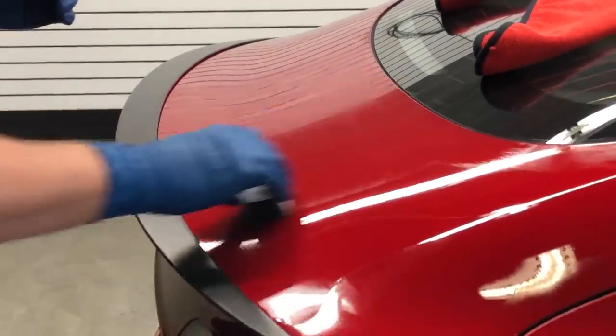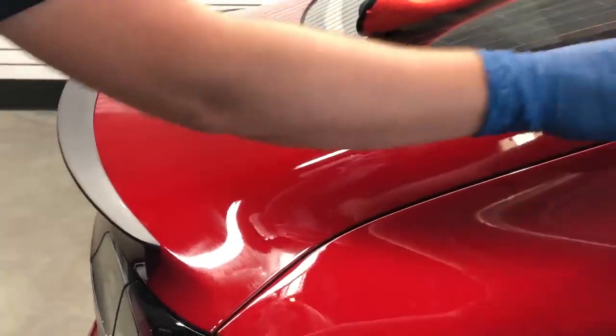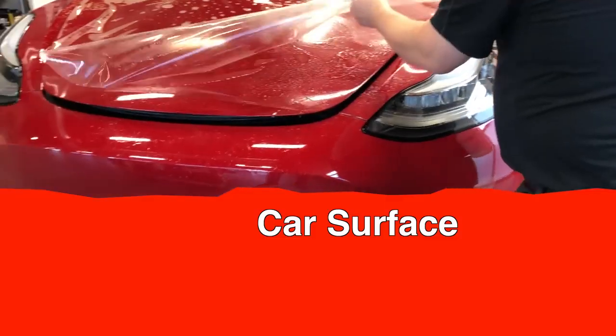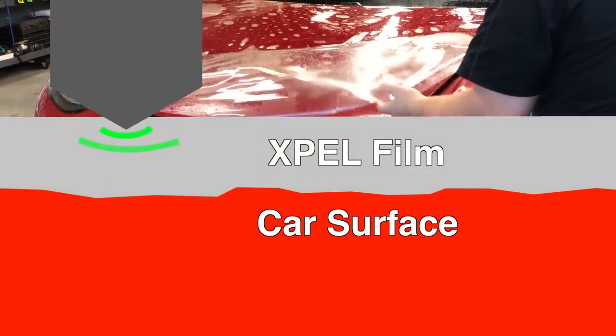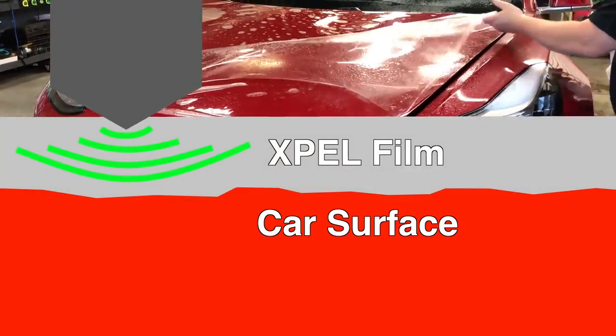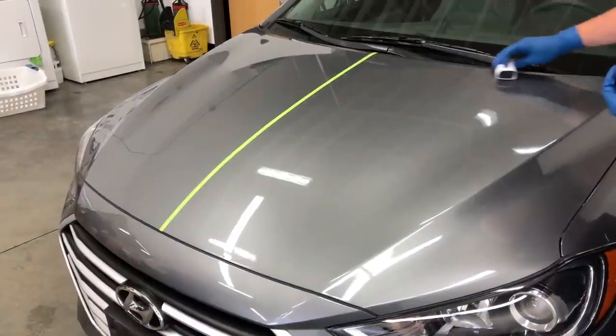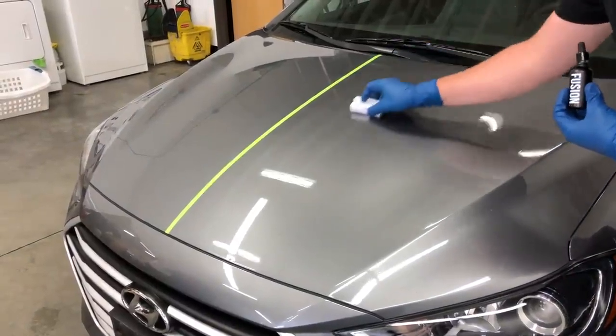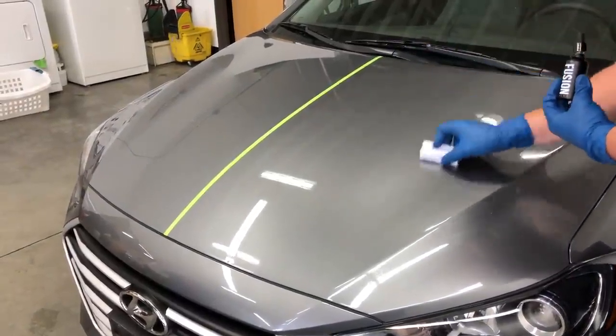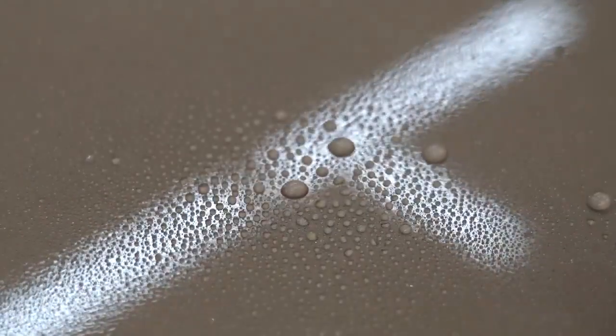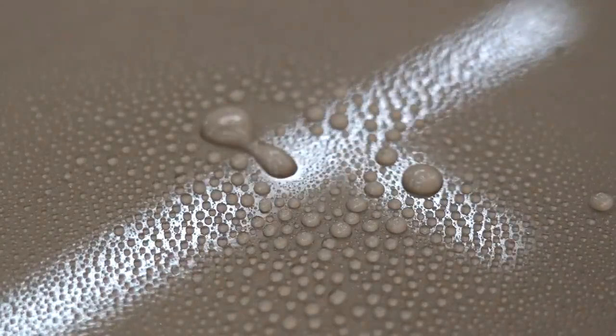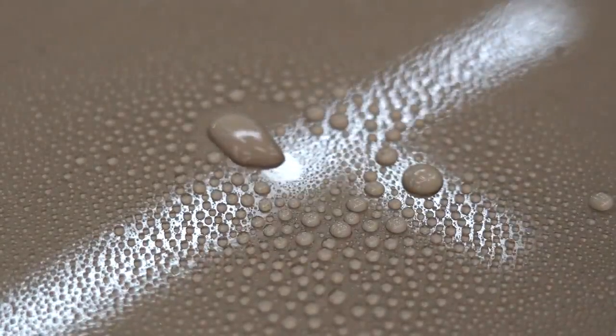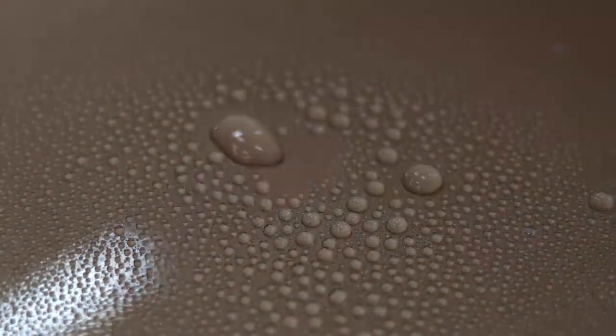Much of this is a result of how incredibly thin the ceramic coating layer is. The flexible protective film helps prevent rock chips by spreading out the stresses of a rock on impact. And because the ceramic coating is so thin, the self-healing properties of that film still work. Here's a quick little test to demonstrate this. We have a sheet of painted metal, then covered in XPEL Ultimate Plus paint protection film, and then covered in Fusion Plus ceramic coating. First, I'm spraying water on the surface to show the hydrophobic properties of the ceramic coating.